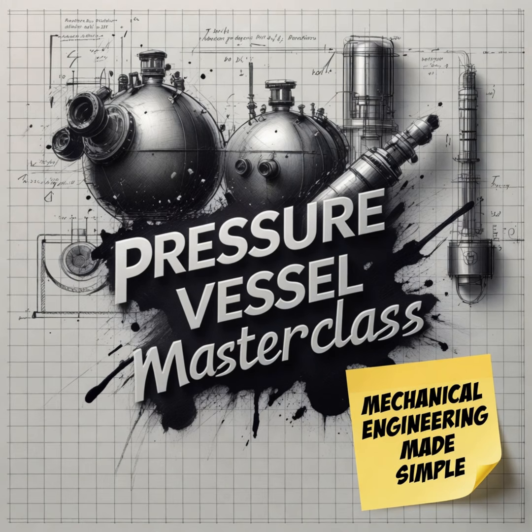Option 3 is more of a process control change rather than a physical design change. You decrease the allowable pressure at that specific low temperature condition. How does that work in practice? You basically write an operating procedure that says, yes, the vessel metal gets down to -20 degrees Fahrenheit during a winter shutdown, but we have interlocking systems to ensure the internal pressure is strictly vented and drops to 20% of maximum during that thermal state. Because if the pressure is low, the stress is low.